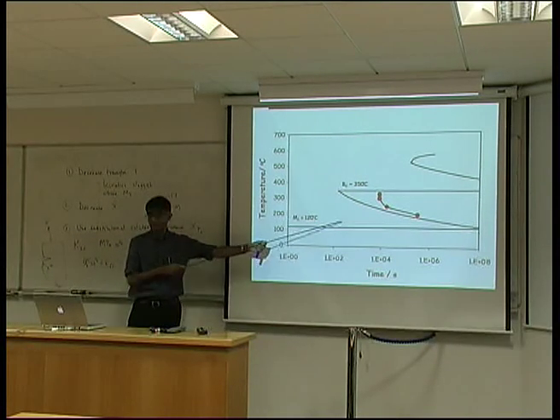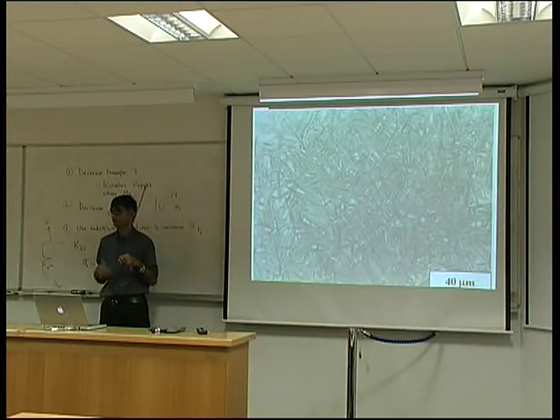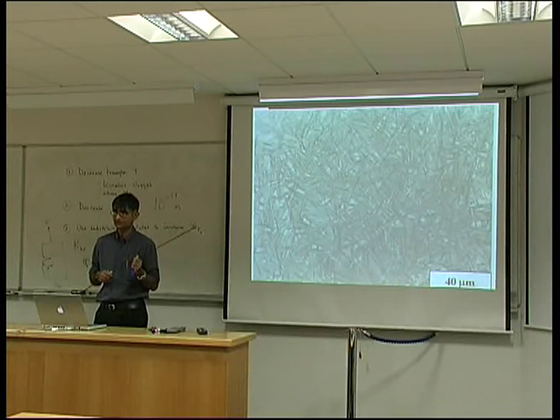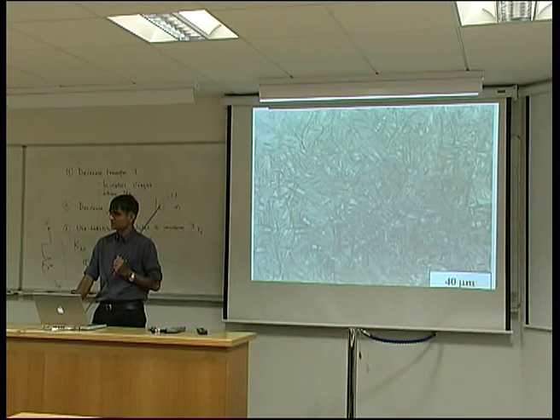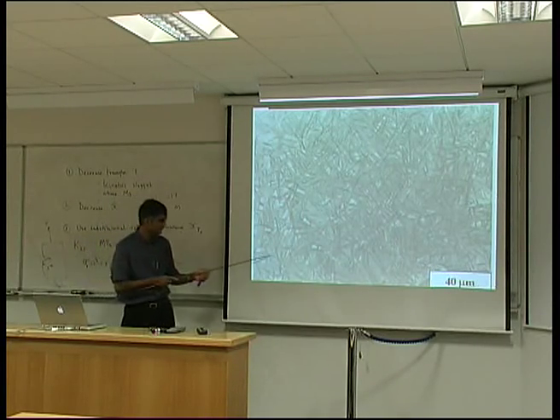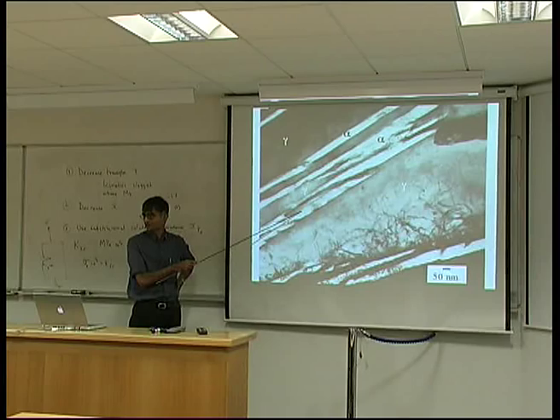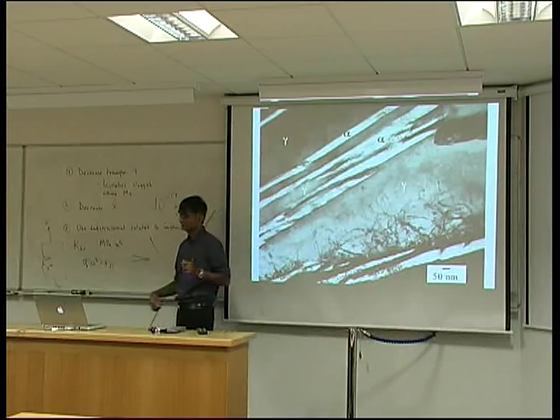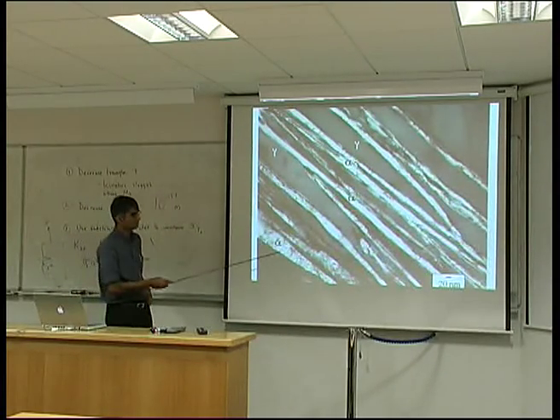The calculated transformation time is comparable to what was measured. Looking at the optical microstructure, it doesn't look remarkable, but the transmission electron micrographs are extraordinary. These show plates of bainite and austenite at a scale of 50 nanometres, and at a lower transformation temperature, the scale is only 20 nanometres. For a plate shape, it is the thickness which determines the strength, because the mean free slip distance is approximately two times the thickness.